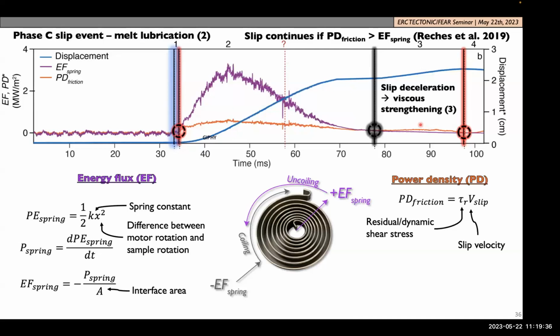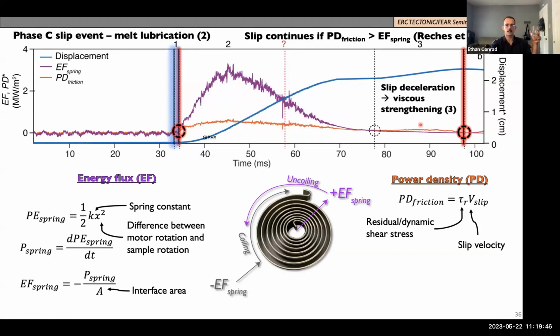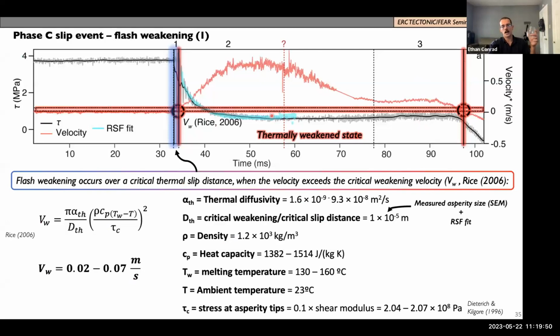So, when you have the individual release, do you really observe a constant residual stress? Let's go back to here, because we have the stress there. Yeah, so it's constant after the critical slip distance, or pretty much. So if you could bracket it here and here, this is where the slip is roughly constant. And then it slightly increases. And if you look at a different scale, you could see this much better. But the strength rapidly goes up here. So once you enter the arrest phase, you have that classic curve with a rate and state fit, where you have the decrease and then later strengthening with continued displacement.